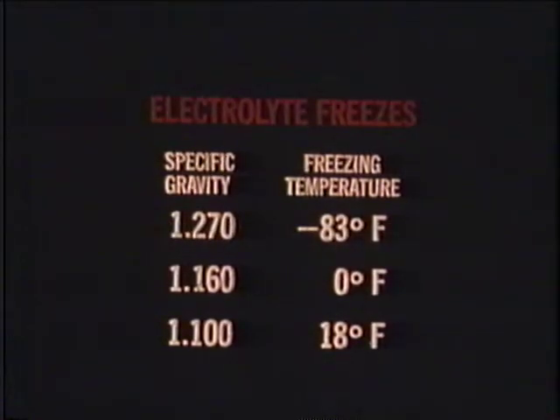The relationship between specific gravity and electrolyte freezing temperature should be carefully observed. Note that there is never any danger of electrolyte freezing if the battery is fully charged. But if the specific gravity drops to 1.160, the electrolyte will freeze at 0 degrees Fahrenheit. Obviously, freezing can occur if precautions are not taken, and battery damage will result.